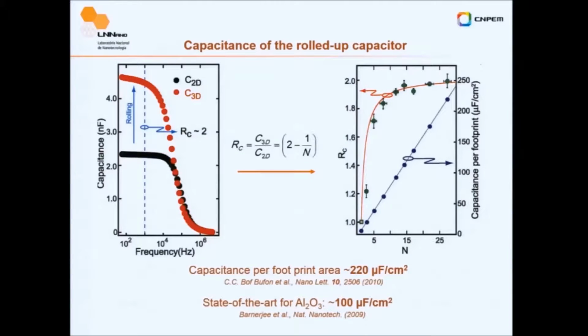You can see here that by that time, 2010, we increased the capacitance per footprint, not by changing the oxide, but by changing the area occupied by the device. So it means you have increased the degrees of freedom. You can change your dielectric material, but you also can change the geometry of your system.